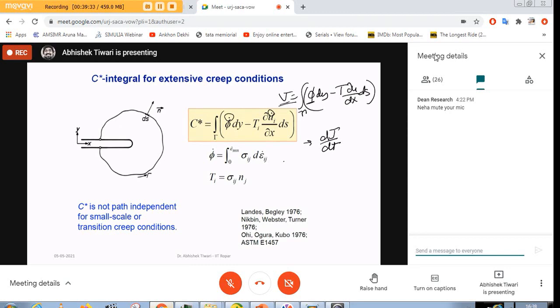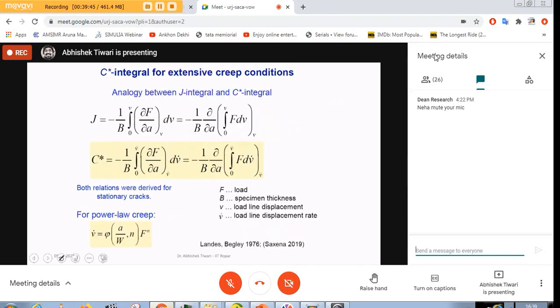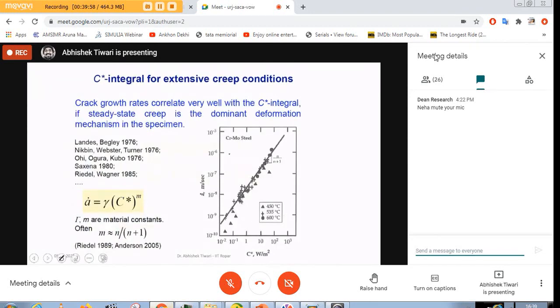But what does C star define? There is no theoretical answer to that. It defines something. It is related to the crack growth rate experimentally. You can calculate C star as you find J integral experimentally, except that you have to change displacement to displacement rate. That's it. And experimentally it is found that in extensive creep condition, this C star value shows a very good correlation with the crack growth velocity, but it loses the theoretical answer of what is actually defined by this parameter.